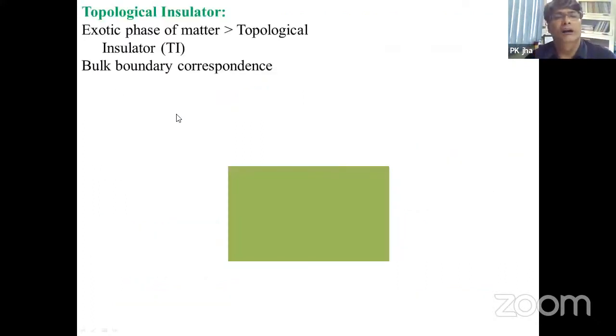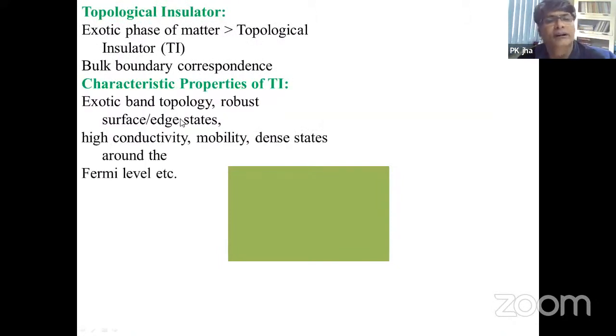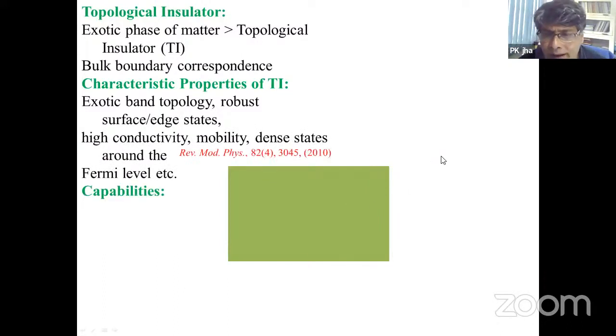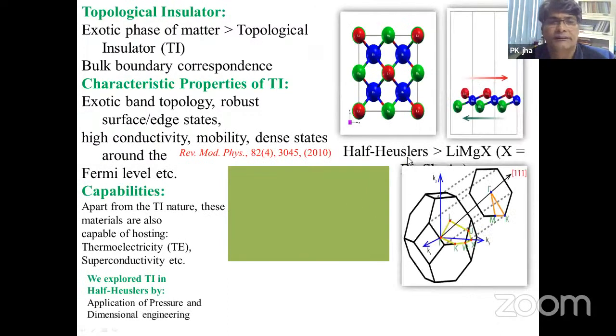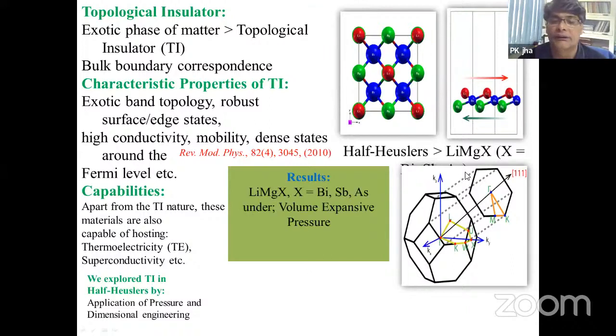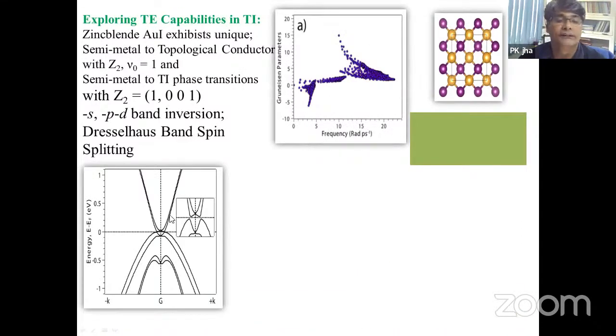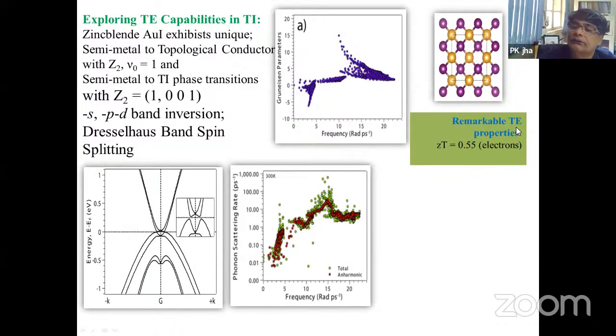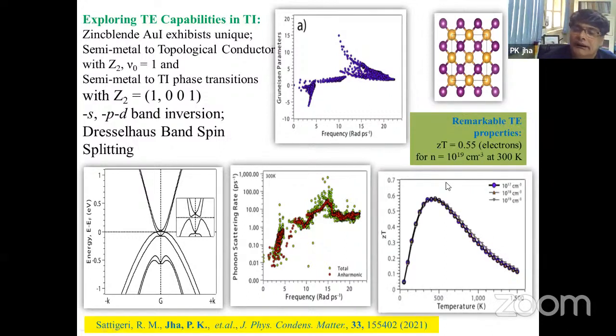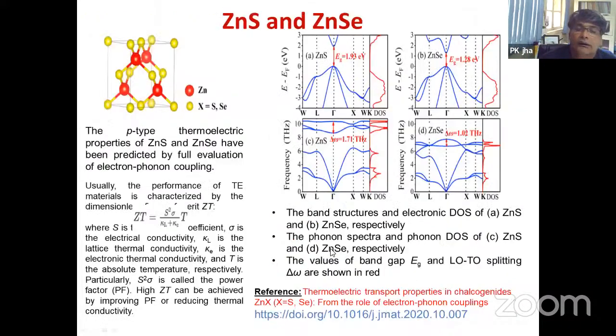Another class of material is the topological insulator, and I will not go into the topological part, but only I will tell you that this is for a half Heusler compound. We have calculated the lattice thermal conductivity, and this is all related to the topology, so I leave it. But you can see here a remarkable thermoelectric property, that is ZT value obtained is 0.55. That is only the electronic part, the lattice thermal conductivity is not basically added, right? So here you can see the ZT with temperature for different carrier concentration, right?